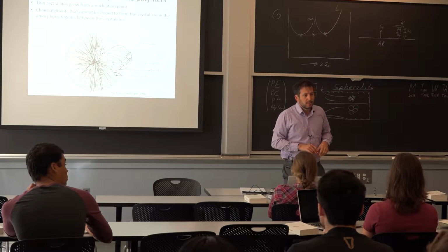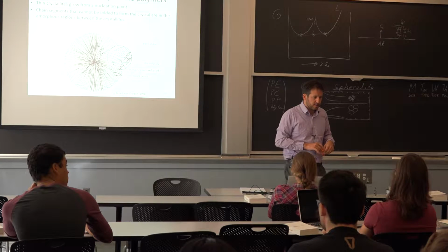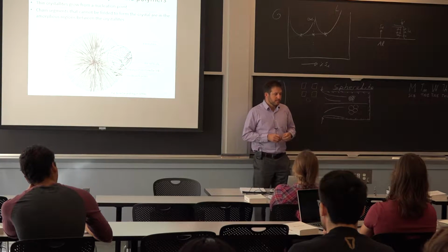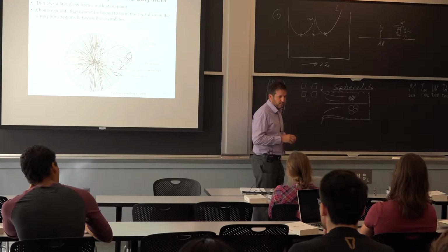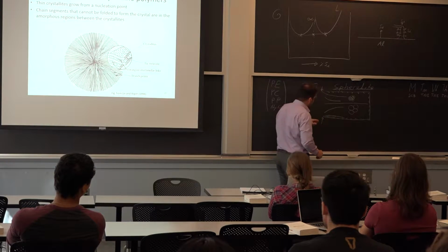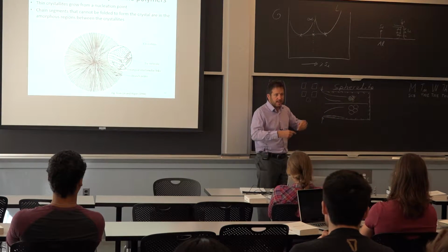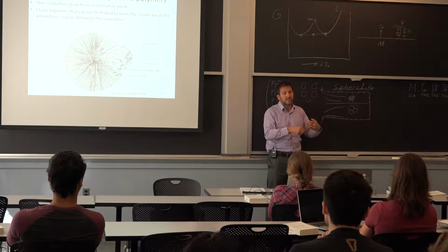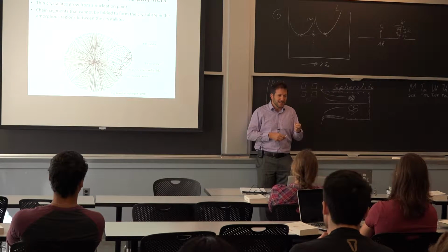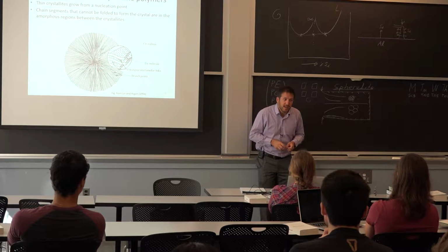Yes? So all those nucleation sites for spherulites form very quickly on the edges. Is that what explains the skin strength, added skin strength in injection molding? It's one aspect. The main aspect of the skin effect in injection molding, I'm glad you're pointing it out, is the flow, because essentially I am having a shear flow going on between my mold and the bulk that's getting shifted here, and that's going to orient the molecules themselves. So it's not just a direct effect of how many crystallites you have. You don't form crystallites as easily because now everything is kind of stretched. And it does have much better properties.